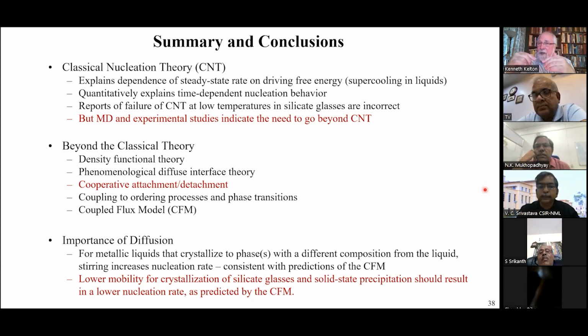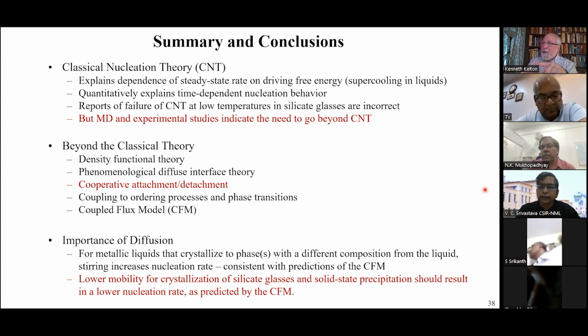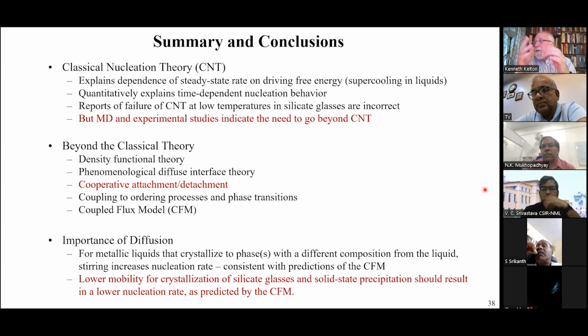But if you take that same alloy and go deeper into temperature, then you can form a stable quasicrystal. And in fact, we did an experiment many years ago now where we showed that it was reversible. So if you heated it up from the quasicrystal into the C14 phase field, it transformed to the C14. If you then lowered the temperature and annealed the solid in the quasicrystal region, it transformed back to the quasicrystal. So it was actually a reversible transformation. So it depends on the temperature you are at, it depends on the interaction and things of that sort. But anyway, I think that's the reason.